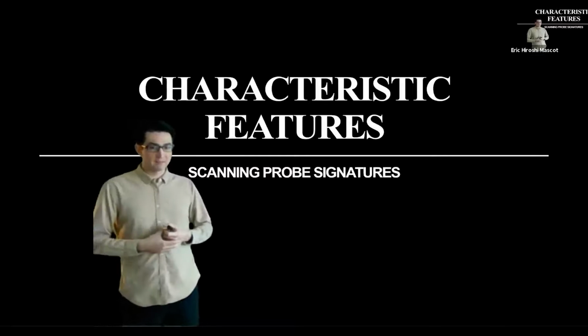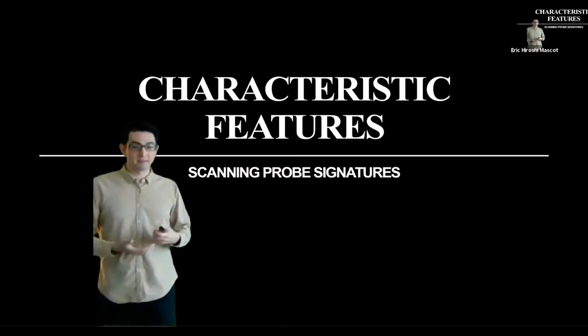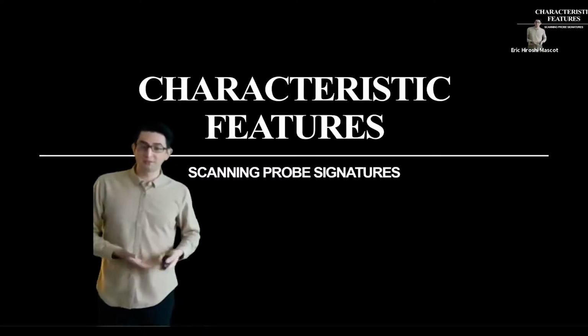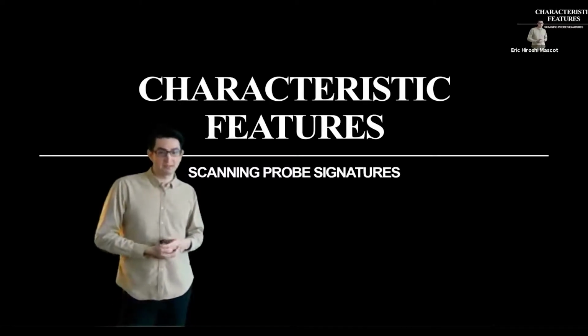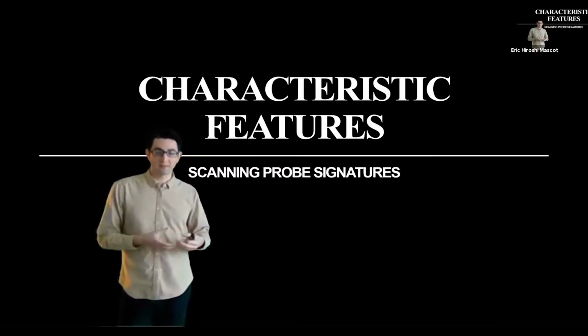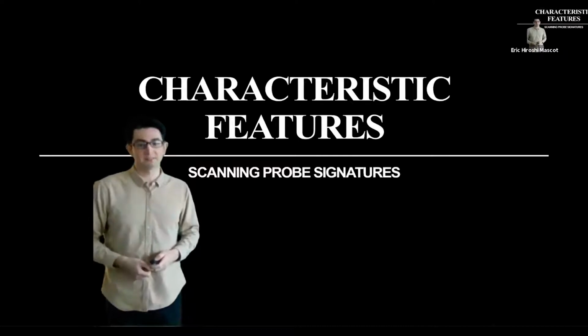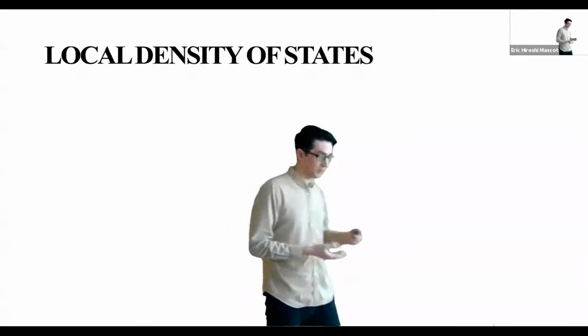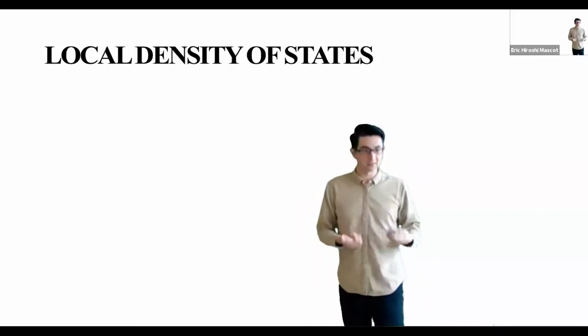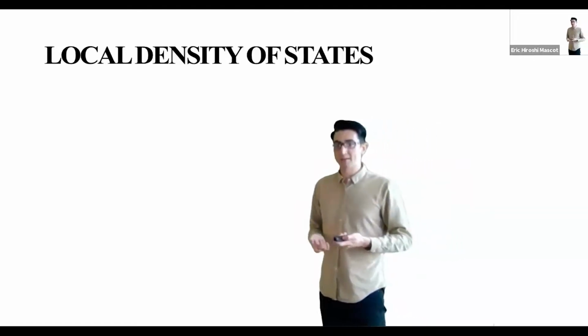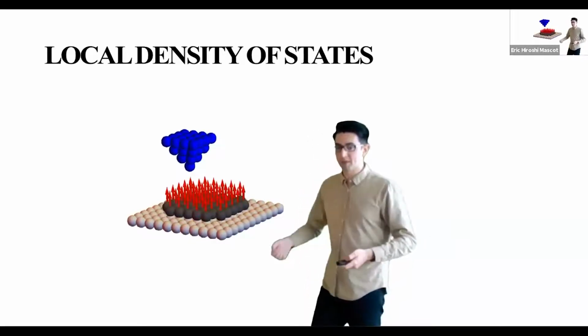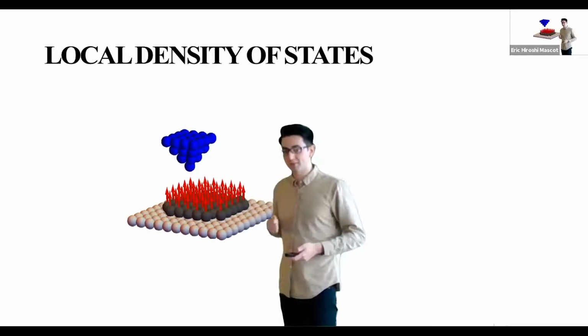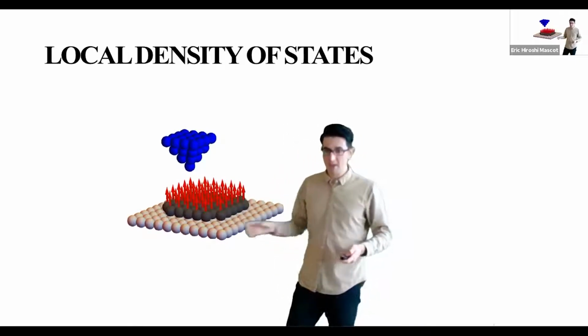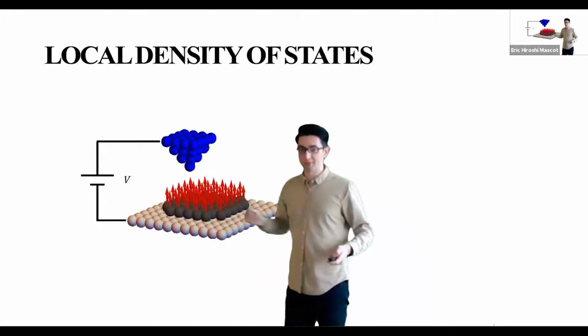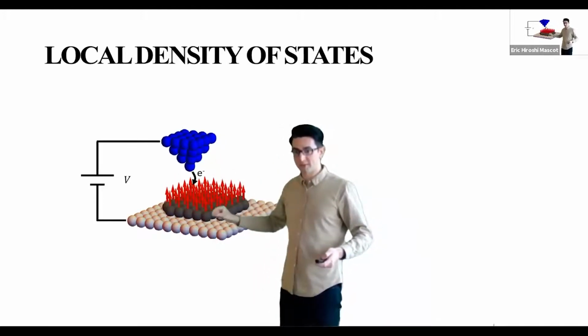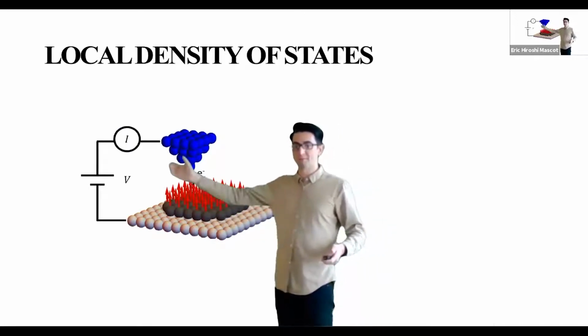Okay, so what will we expect to see in an experiment? One useful feature about these magnet superconductor hybrid systems is that we can use scanning probe techniques to look at local features on the surface of the system. And we're interested in the local density of states to find the zero energy Majorana modes. To do that, we can use a scanning tunneling spectroscopy experiment, where we bring a very sharp tip very close to the surface of the system, and then we can apply a voltage between the two. Then the electrons will tunnel into the system, and we can measure that current.